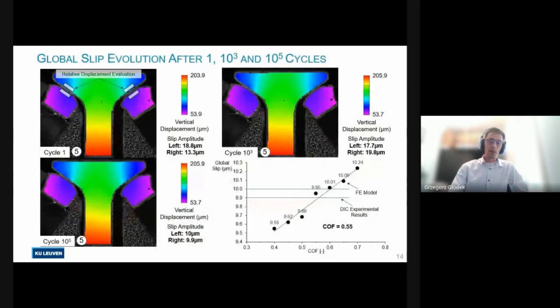Now, those results were also later used to determine the coefficient of friction that could be used in finite element simulations. So displacement fields were extracted from the areas close to the contact edge and then transformed to align them with the direction of relative displacement. Now, initially, the values of slip are quite different. And even though after 1,000 cycles they become closer to each other, they're still quite high. So it's very likely that we are still dealing with some initial running-in phenomena. And only after 100,000 loading cycles, we can be sure that the setup is in a stable condition.